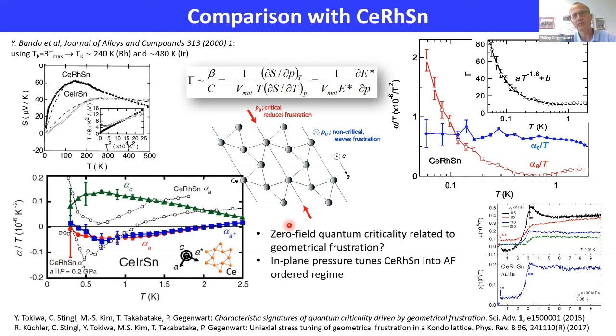And there is also a related sister material, cerium rhodium tin, where we just replaced iridium by the isoelectronic rhodium. In the rhodium case, the T_K is about half of the size, like in the iridium. And in the rhodium case, we can also induce negative thermal expansion under in-plane compression. And we also observed that the in-plane thermal expansion coefficient shows a divergence as if we had a quantum critical point which is tuned by the in-plane uniaxial pressure. And this may be actually a hint that the geometrical frustration, which is of course modified as you apply the pressure in plane, is very important in determining the ground state of this material.